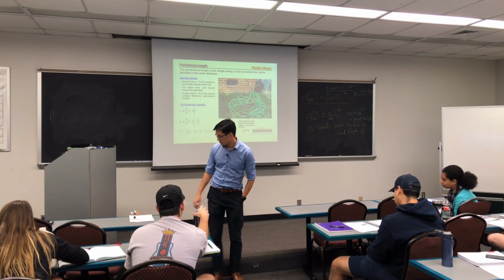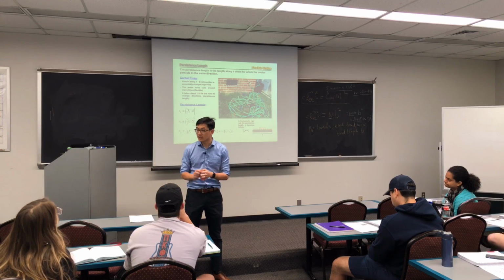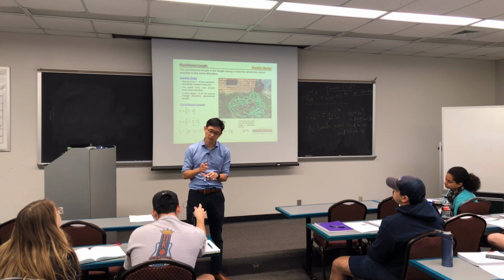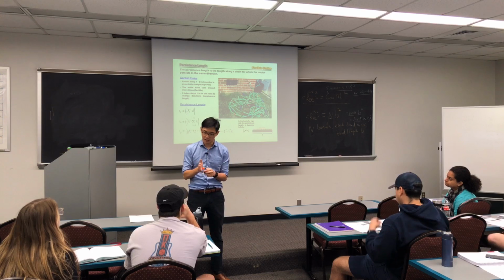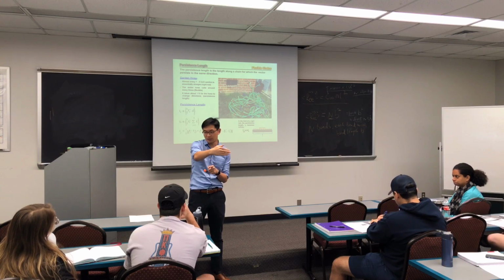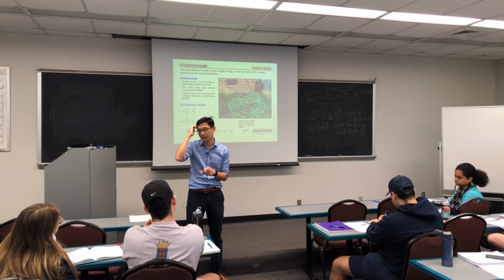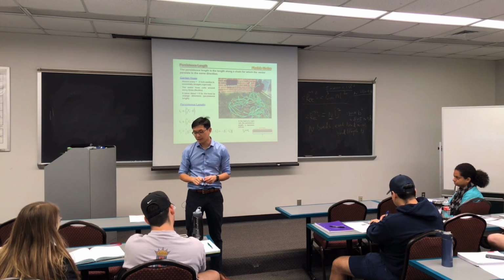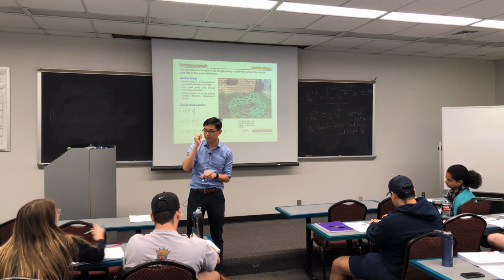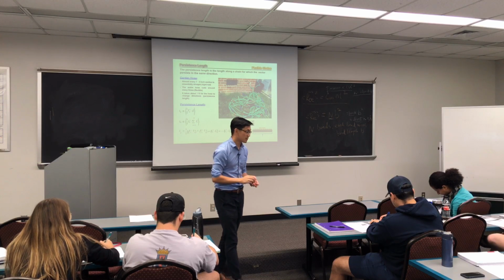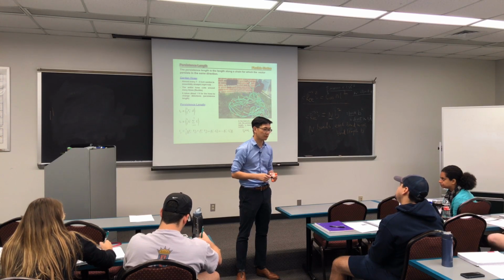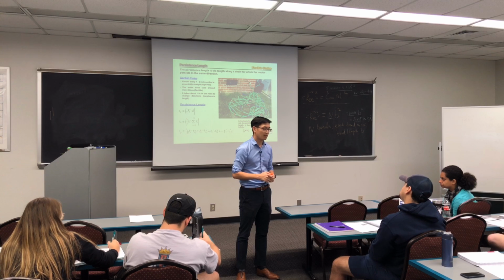And I have a better way to explain what persistence length is physically. It doesn't mean you cannot bend a little bit. It's actually roughly the persistence length when you start to see the chain bend 90 degrees. So your chain is going straight for the first bond. If you count how many bonds until statistically your chain is turning 90 degrees, that's a persistence length. Polystyrene took about 5 bonds to bend to 90 degrees. The material I play with, conjugated polymer, takes about 20 nanometers, which is 20 times more rigid than polystyrene. Quite amazing.